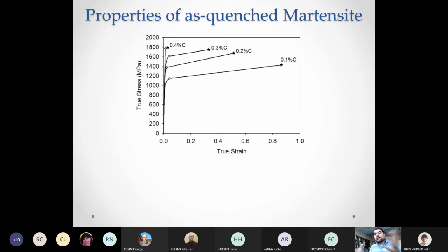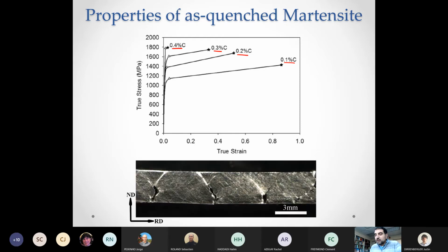And to make a benchmark for comparison, we took that alloy, we decarburized it to different levels. So this is the alloy when you have 0.1% carbon. You could see it has high ductility, 0.2, 0.3, and of course 0.4 in the as quenched condition. The material is not ductile at all. It's strong, but it's very brittle. And if you try to deform the as quenched material with 0.4% carbon, it breaks right away. So this example here was a case where we tried to cold roll the material, and you see immediately how it fails along the shear planes. The total deformation before the sample failed was practically zero. It immediately failed during rolling.